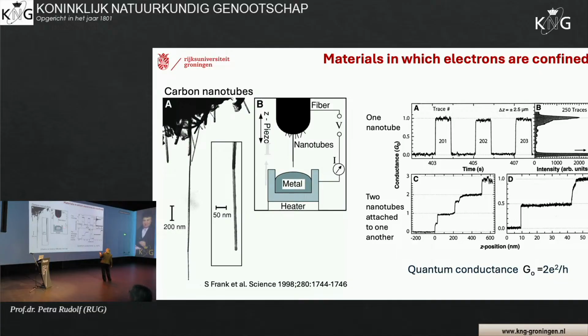When you go in, it doesn't matter how much you go in the beginning, you always get the same value. So it is really on-off as a measurement. And you see that the conductance goes up in steps. And sometimes you see a double step. This is when you have, like here, 2 nanotubes which are attached to one another.